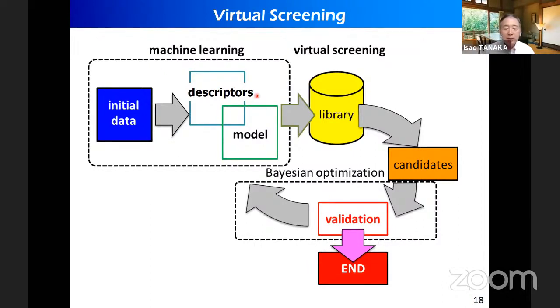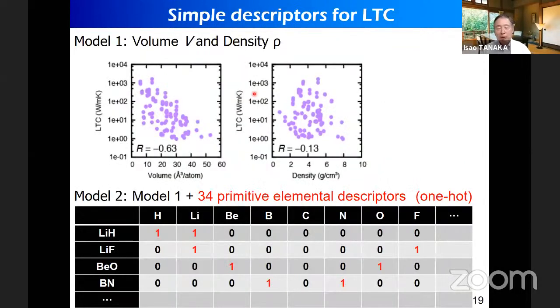Probably you are interested in which kind of descriptors, very sophisticated descriptors or not. As a matter of fact, our descriptors are very, very simple. One is crystalline volume, and the other is crystalline density. You can find that the correlation between the volume and lattice thermal conductivity is not that good. It's very widely scattered. But with density, there is almost no correlation. But we use them because they are very simple and available for all different kinds of crystals.